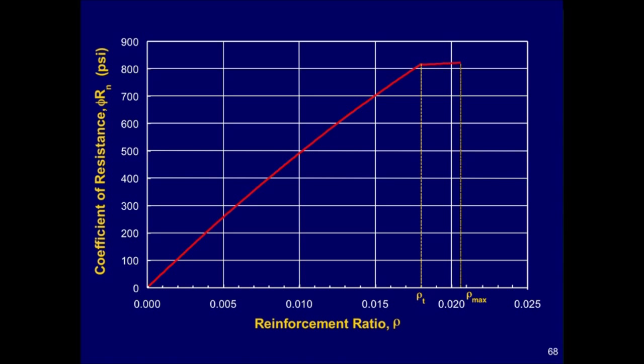In particular, it shows what happens when the limit for tension-controlled sections with phi equal to 0.9 is passed. Similar curves can be generated for other material strengths. The reinforcement ratio corresponding to phi equal to 0.9 is rho sub T. Once more reinforcement above rho sub T is added to the section, the strength gain is minimal up to the maximum reinforcement ratio rho max. The reason for this is that any gain in strength with higher reinforcement ratios is cancelled by the reduction of phi when the net strains are less than 0.005. Therefore, flexural members should be designed as tension-controlled sections whenever possible.